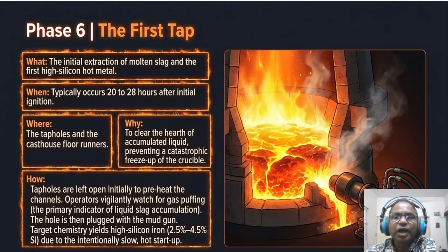So note the target chemistry. We are looking for high silicon iron, where the usual figure is 2 and less, and here it is 2.5 and less. So this is intentional. High silicon content ensures the metal stays hot and fluid in a steel-warming hearth. The first cast clears the crucible of accumulated liquid, preventing a catastrophic freeze-up. It is the definitive proof that our thermodynamic calculation for the coke blank and the wood filling were correct.